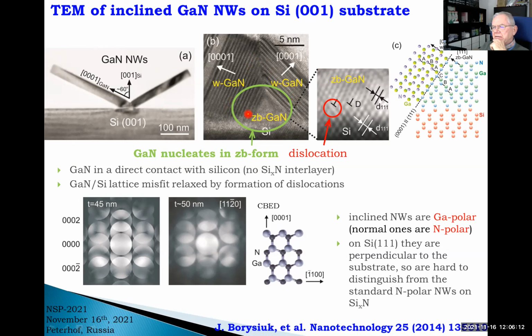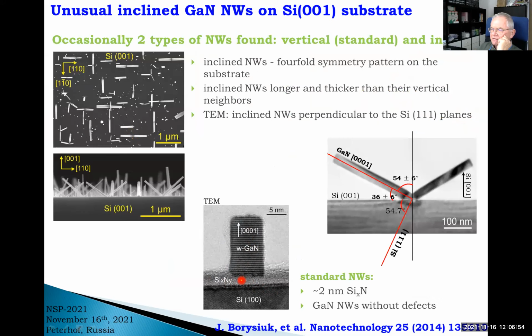zinc blende pyramid at the beginning, and then from the side walls, these two arms appear and they are wurtzite. Because there is a direct contact of this gallium nitride with silicon here, we have all the phenomena, we have misfit dislocations, everything as expected in lattice-mismatched systems. Importantly, these wires are gallium polar. So the point is that if we have these wires on silicon 111, they would be perpendicular to the surface, so we could not distinguish them from these regular ones growing on top of silicon nitride.